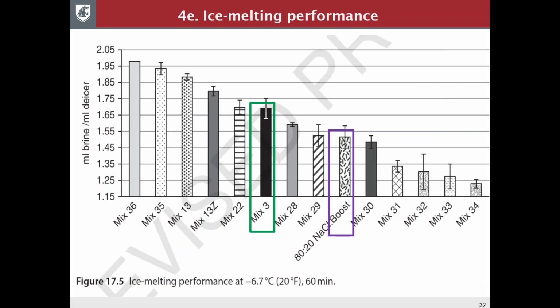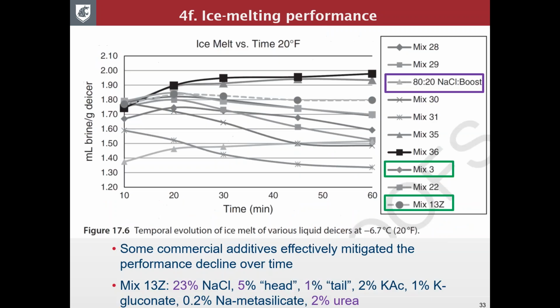And at 20 degrees, in this case, we actually compared not just to the salt brine, but to the product they tend to use for colder temperature. At 20 degrees, they basically blend salt brine with Boost at 80 to 20 volume ratio. Their challenge was the Boost additive was a relatively expensive commercial additive. So blending at 20% significantly increased the cost of the liquid deicer. In this case, we could potentially replace that brine blend with mix 3. As you can see, the performance is still much better. We actually tested significantly better in terms of the p-value in statistical terms.